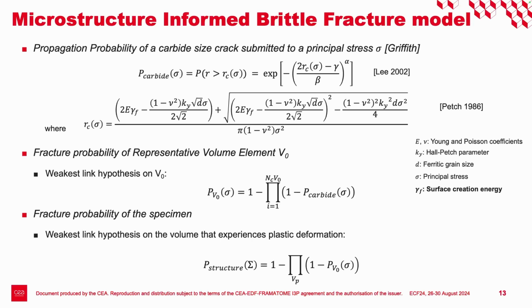But here we will modify a little bit the critical size, which is not just a Griffith criterion. We use instead a modification of this critical size that takes into account D, which is the ferritic grain size, because we have seen that the HMM material has a much larger grain size. And this comes from the model of Petch published in 1986, that says roughly that if you have a larger grain size, then it's easier to have a longer pileup of dislocations that can help open more easily even very small cracks that have been initiated on small carbides. So you have to consider smaller carbides for crack propagation. That's why if you increase D, you reduce the critical size.